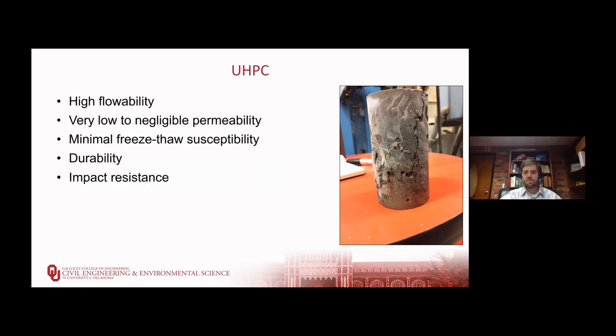It has a very high flowability, a very low to negligible permeability, and minimal freeze-thaw susceptibility, which leads to a very high durability and hopefully very extensive long-term performance. And those steel fibers included in the matrix not only help with tension strength, but also provide some impact resistance, which can be very helpful in some transportation applications.